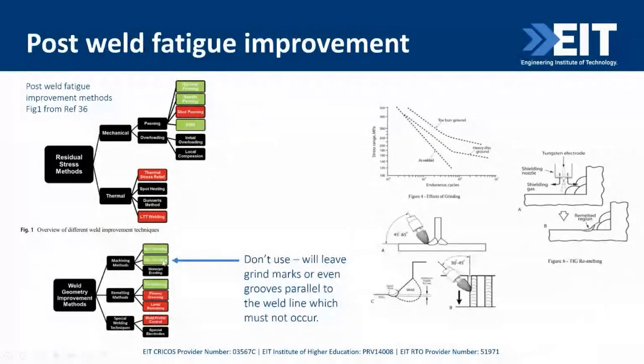Disc grinding will leave you where your marks are always going to be parallel with the weld. Your line of your disc is parallel to the weld, so your marks and grooves are parallel to the weld, which is terrible for your stresses, which are mainly perpendicular to the weld line. So please don't do that. If you want to do that for very rough weld material, do it. Make sure you've got no grinding marks left, and you finish off with a burr grind.